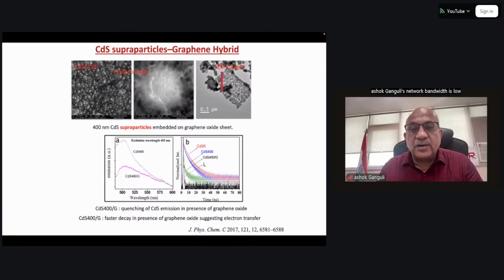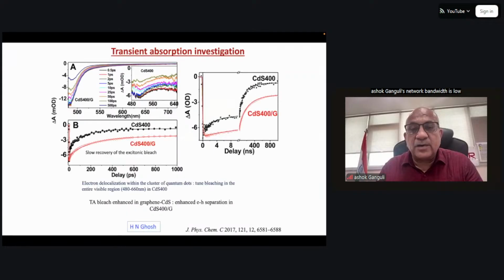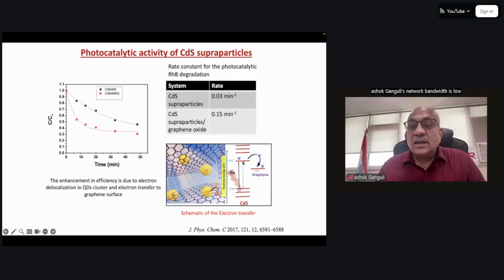This is something called bleach recovery. This takes a lot of time to recover. And if there is no graphene oxide surface, then it is faster. And that means the lifetime is more when you have graphene oxide. Okay, so this is what I said, that electrons get transferred on a graphene, although it's written graphene, actually it's graphene oxide. And once it is transferred there, it is moved away from the site. That means those electrons can be effectively used for reduction.